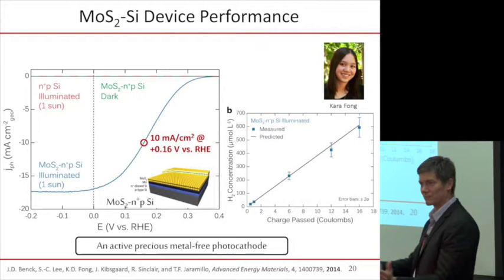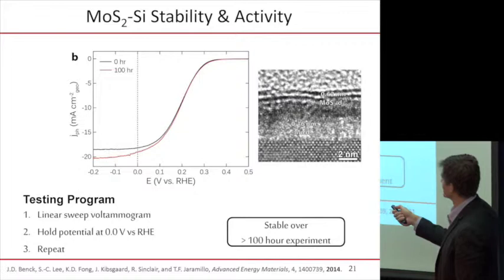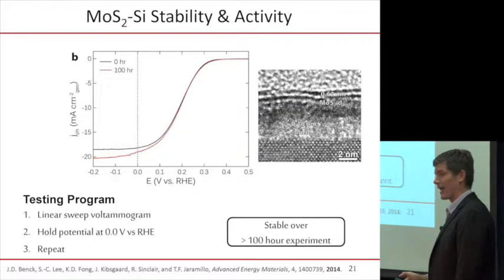We also did a stability measurement. We found that after 100 hours of illumination, even though this is only about 2 to 3 nanometers of MoS2, that was able to protect this thing in sulfuric acid. Silicon does not want to be hanging out in sulfuric acid.